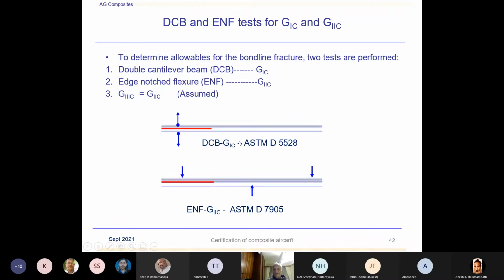Let me tell you, what you will find from the ASTM standards using these tests is still you might have to manipulate or juggle around to find really the initiation, and it's not easy. It looks simple, but when you are trying to determine the right value of G1C, you find lots of scatter when you have analyzed the data for G1C and G2C. And then you have to fix up your criteria. What is my criteria in order to define G1C? Initiation or 2% growth or 5% growth, those criteria, I tell you, you will find a lot of variation in that. So it's a bit tricky to interpret the data from tests for this coupon. However, that's the way it is done now.